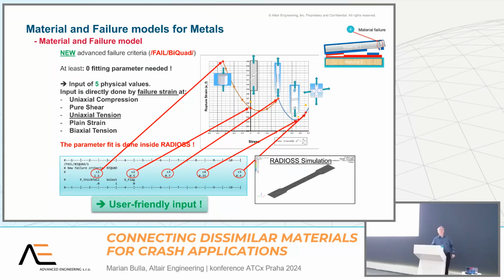For sure, we also developed a new failure model, which is biquad, which is even simpler: 2 parabolic equations with an intersection point in uniaxial tension, which gives you a much easier way to use it. Just enter here the failure strain for fracture in case of compression. Here you add the failure strain for shear. Here from the beautiful tensile dog bone test, for example. Here is plane strain, and here is biaxial failure, for which you can use this kind of test, or a punch test, which means a sphere through a plate, whatever. So there are different geometries or test methods here. Just ask your test lab, and then you can go for validation.